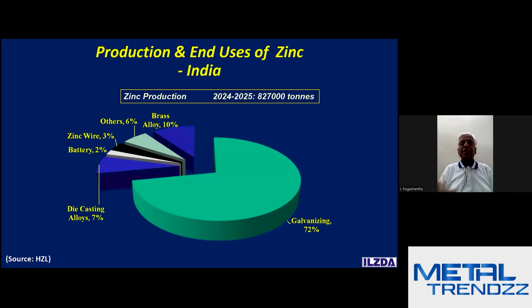There's another waste product, iron and zinc. The free iron comes from the pickling bath, iron salt, or the job itself. Zinc and steel also react, and it forms a thicker, heavier material called zinc dross, which settles at the bottom of the kettle. Therefore, you have zinc ash on top, molten zinc, and zinc dross at the bottom. Both the zinc ash and zinc dross have a ready market in this country. Zinc ash is used mainly for manufacture of zinc sulfate, mainly used for agricultural applications.